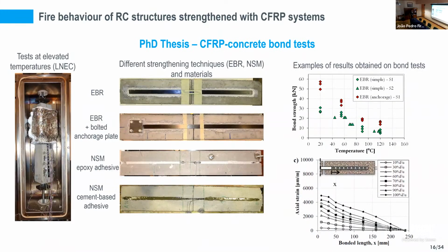Regarding the first part, the study about the bond behavior of the CFRP to the concrete, we decided to investigate the influence of different parameters that I will not describe in detail here, but we studied the influence of different application techniques. So EBR, which stands for externally bonded reinforcement, where the CFRP is bonded at the surface. And we also investigated NSM, where the CFRP material is bonded inside grooves that are opened in the concrete cover. And we investigated the influence of different parameters, different configurations, and different materials.